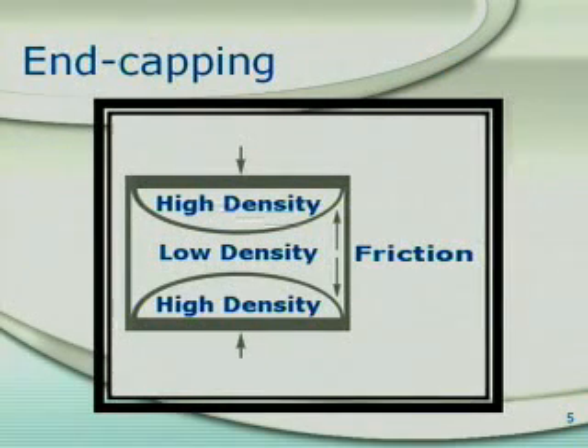End capping is a result of the friction between the die wall and the powder and creates areas of high and low densities within the pellet as shown in this diagram. These will eventually split apart at their boundaries during further processing. Cold isostatic pressing is done after uniaxial pressing at higher pressures and will not result in end capping because the pressure is applied in all directions and without a surface to induce friction.